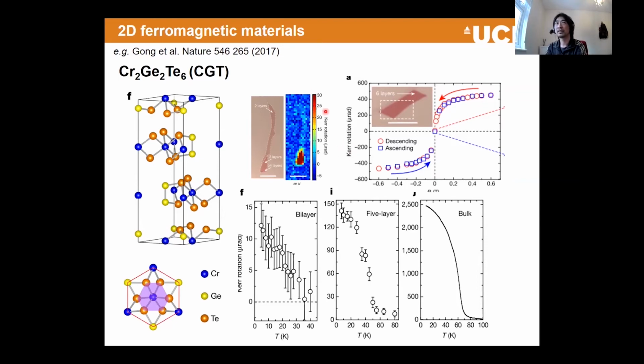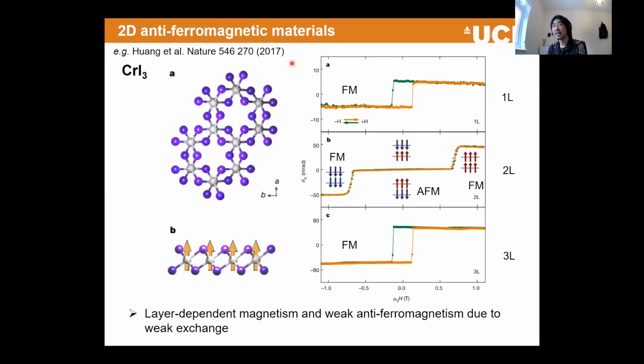That development was published in 2017, and at the same time there was a similar material with a different cross-over. In this case, these are 2D antiferromagnets. I want to explain that the magnetic ground state can be controlled by the number of layers. When you have one layer, the chromium moments can be polarized and have a ferromagnetic state. They just align in the same direction. Now, when you add an extra layer on top of it, the second layer wants to polarize antiferromagnetically coupled to the first layer.